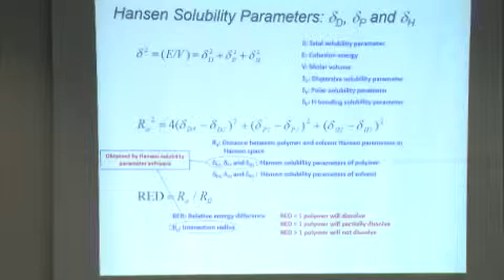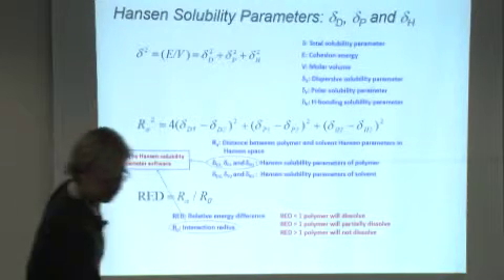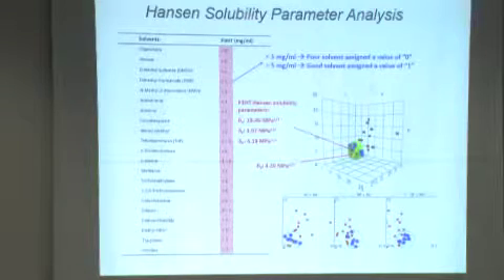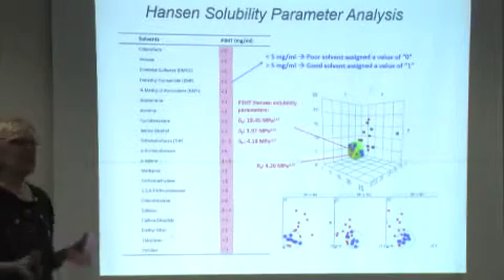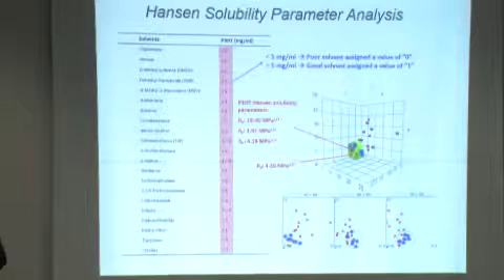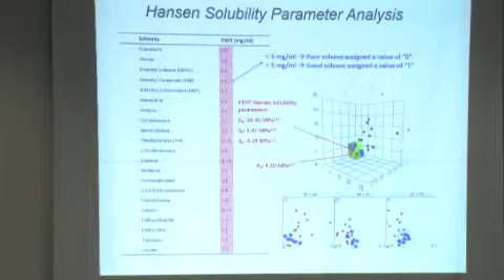So we started exploring what may be going on here. And one of the things that we used were the Hansen solubility parameters of the solvent system and its relationship to the polymer. And then by doing an analysis of the solubility of P3HT in a number of different solvents, we could define a parameter space where we have good solvents versus poor solvents for poly-3-hexylthiophene and start to explore what the impact of solubility is now on device performance.